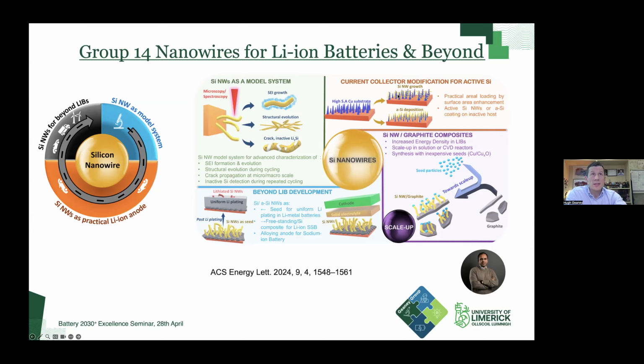One thing to notice on these current collector modifications, and I think the literature has caught up to this, is any inactive mass that is added to the system will by definition dilute the energy density that's possible. Okay, so if you have a super complicated 3D architectured current collector, you may have completely diluted any of the energy density benefits that you might have gotten from adding in silicon. So what you need to do is have these lean systems where you minimize the dead mass that is in your system. And one way of doing that is almost in between. So it's coming up with these silicon nanowire graphite composites.